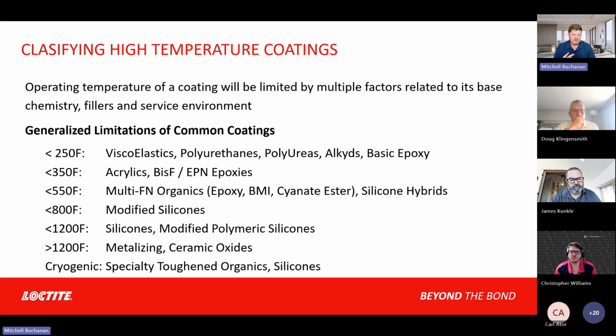And then this is also where, in this 550 Fahrenheit range, your silicone hybrids are going to fall, silicone alkyds, silicone acrylics. Then you take another step up into that 800 Fahrenheit continuous operating temperature, and that's going to be primarily dominated by modified silicones, along with some basic higher temperature silicone polymers. And then after that, you step into the true inorganics, which is going to be silicones, and then your modified polymeric silicones, multipolymeric matrices, and that's going to be your 1200 Fahrenheit continuous operating. A lot of these will be able to do temporary peaks, accommodating startups and different process interruptions, up to 1500 Fahrenheit without negative impacts to adhesion or color gloss, etc.